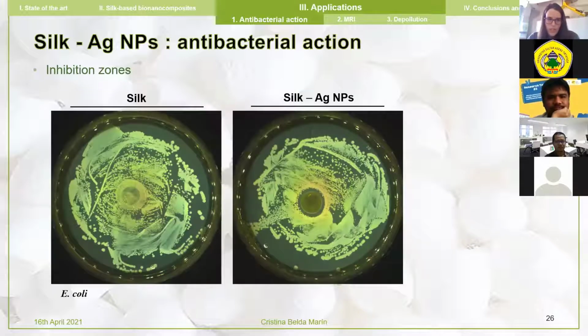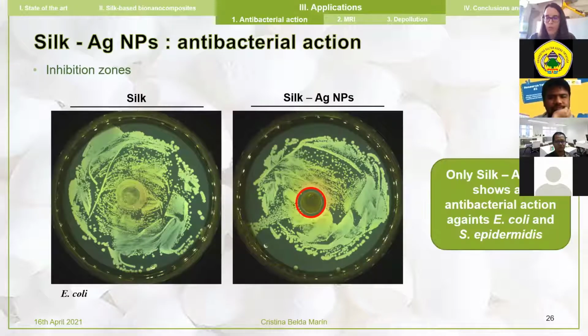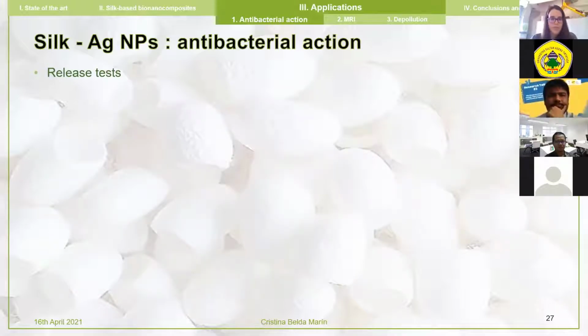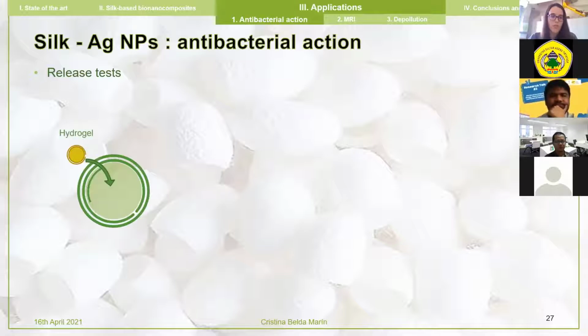So here you have the results for E. coli, in which you see that for silk hydrogels, bacteria are happily growing next to the hydrogel. However, for silk with silver nanoparticles, a surrounding area of inhibition is seen, and bacteria are not able to grow. We have unexpected antibacterial action. We wanted to know whether this antibacterial action was due to a release of silver ions, as it's explained in the literature for most of the cases.